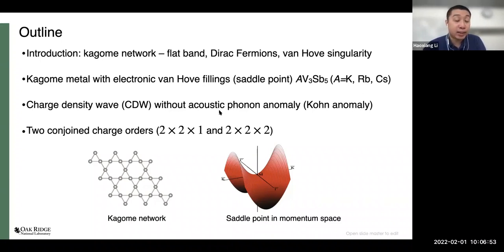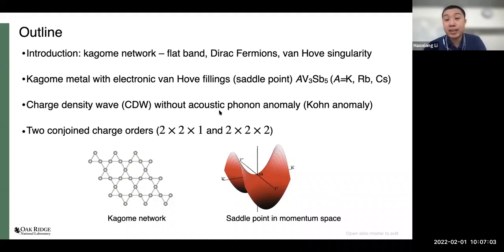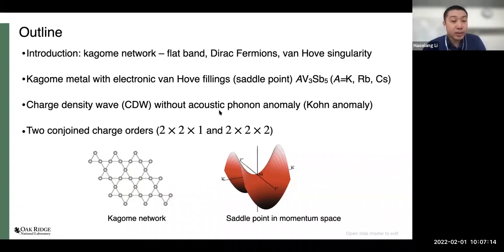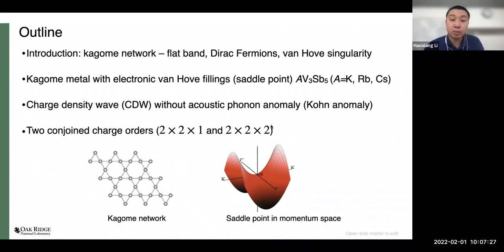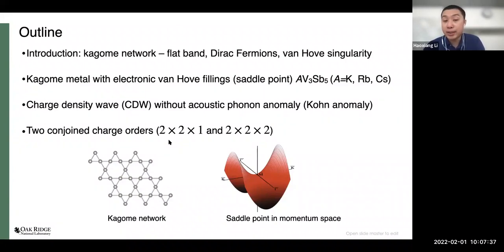This is an unconventional charge density wave in that it does not show any Kohn anomaly or acoustic phonon anomaly, which is typically a signature in conventional charge density wave in previous theories going back to Peierls transitions. More strangely, this charge density wave actually contains two different charge orders emerging in the same CDW transition simultaneously — one in-plane order and one out-of-plane order — that coexist and are intercoupled, but can be separated under high pressure.